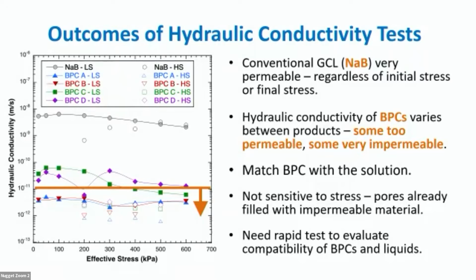The BPC GCLs, on the other hand, were very impermeable. We saw in our low stress tests 2 GCLs, the red and the blue here, A and B, that had very low hydraulic conductivity. And this is really drips per week, actually, of liquid flowing through these systems. Very, very impermeable. That met our standard. 2 that were just above. These were the low stress tests.